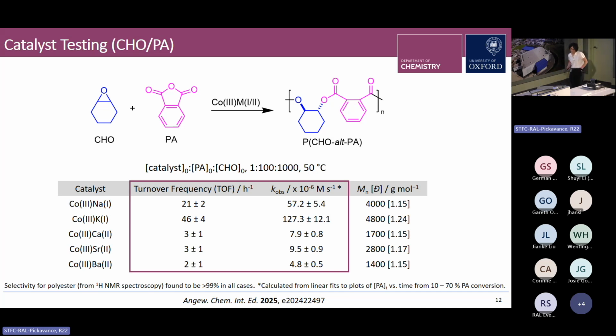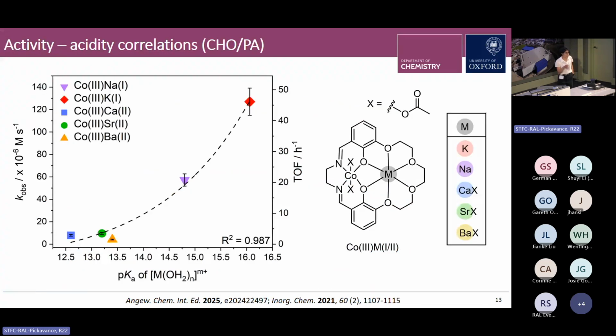frequency and the K-obs. And most notably, the cobalt-3 group 1 metal catalyst significantly outperformed the cobalt-3 group 2 metal catalyst. And of the group 1 metal catalysts, the sodium and potassium, the cobalt-potassium combination is the most effective. So in order to further understand or rationalize these results, we plotted these activity values versus the S-block metal Lewis acidity, as quantified by the pKa of the corresponding S-block metal aqua complex. So those x-axis values are taken from the literature. And what we see is this exponential increase in catalytic activity with decreasing S-block metal Lewis acidity or increasing pKa.